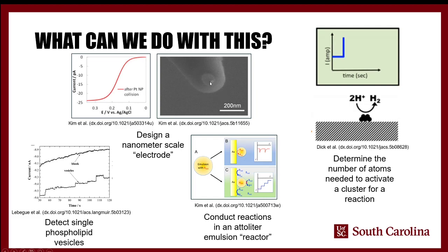But here, what they actually did was put the insulating layer on again, and then electrochemically reduce platinum salt, the platinum tetrachloride, onto the insulating layer via the same tunneling mechanism. And in doing so, they could get platinum particles that were as small as about 10 nanometers in diameter.